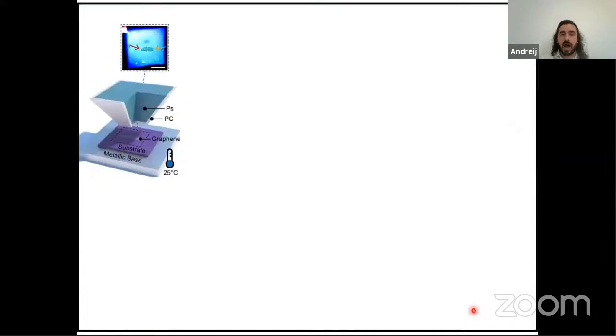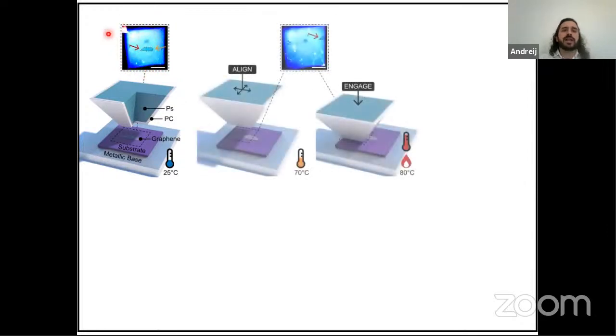And now I'll show how we use these pyramid stamps to prepare twisted bilayer graphene samples, okay? So we use our pyramid stamp and cover it with a polycarbonate polymer, and we have our graphene here, which is on top of a substrate, which in turn is on top of a metallic base. And here's an optical image of our graphene flake and also the pyramid.